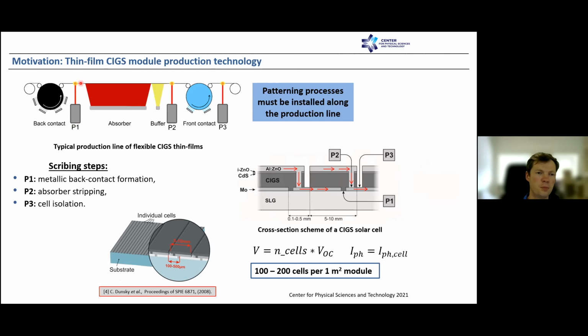When we have a P1 process, we have metallic back contact formation or the division of the cells. Then when we have absorber layer and buffer layer deposition, we have laser stripe P2, where we do absorber striping. And after the front contact deposition, we have cell isolation, so the P3 stripe. And what we get is cells interconnected in series, and here some red arrows represent the current